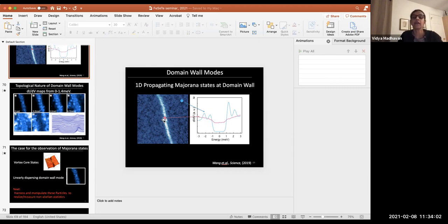The problem is that this is not a topological superconductor in the non-conventional sense. If you truly had a topological superconductor, then at the boundary of the topological superconductor, just like in a topological insulator, you would expect to see 1D propagating Majorana fermions. But for this particular scenario where you have a proximatized topological insulator, only in certain circumstances do you see these propagating modes. So you would not see these propagating modes at the boundary between this superconductor and a trivial superconductor. That's not the scenario in which you realize these kinds of helical Majorana fermions. The scenario is very strict. You have to have a pi phase shift or some kind of phase shift in the superconducting order parameter.